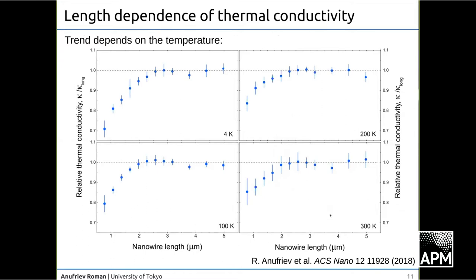But clearly heat conduction becomes less and less ballistic as we increase the temperature, which is logical, because we reduce the wavelength of phonons and we reduce the mean free path, so heat conduction becomes more diffusive. At room temperature, it's really like 10% ballistic, maybe 15%. Nothing close to 100% ballistic transport, as is sometimes reported in